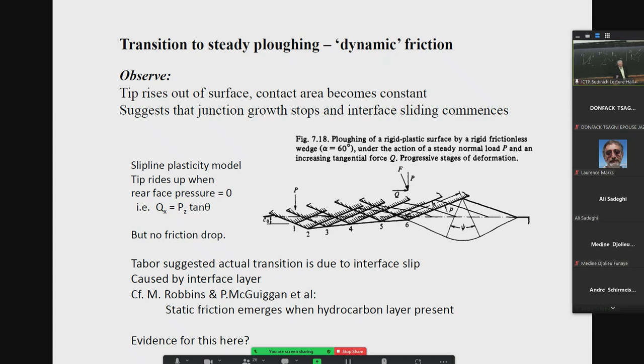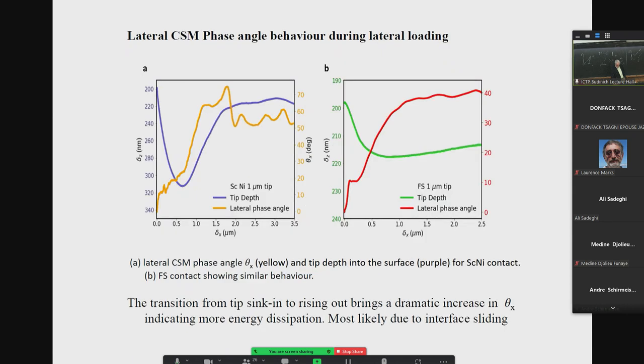Question is, is there some evidence which we can add from this experiment to say, is there actually some slip occurring in the interface at this point? And of course, this is the point at which we took some more recent data, measuring at the same time the phase angle between the oscillatory force we're applying and the displacement response. As that increases, it's an obvious signal of dissipative energy. You see what's happening here, right? In the case of the